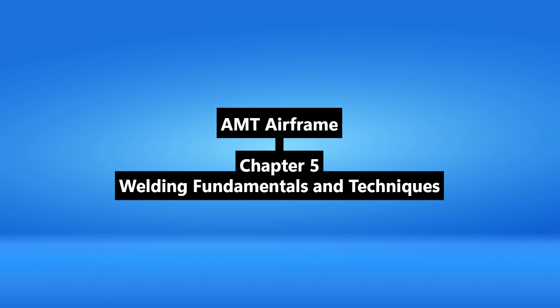Utmost care. Cleanliness and shielding are everything. Ideally, weld in a clean room, controlled humidity, no drafts. Use DC straight polarity, water-cooled torch, large gas cup, maybe gas lens for smooth flow. Thoriated tungsten recommended. Shielding is critical.